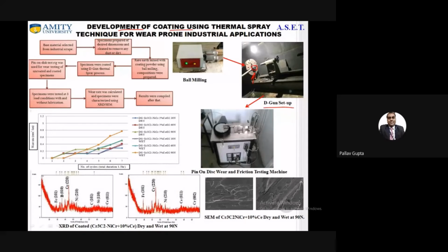So next, we have studied the wear characteristics, in which we have done the wear characterization at variable load and variable conditions. That means wet condition, dry condition, semi-wet conditions, all these conditions we have done the characteristic studies. And then we found that for the 5% and 10% addition of cerium oxide, the 10% addition of cerium oxide in both chromium carbide nickel chrome gives superior coating characteristics. And that has been verified with these particular SEM micrographs also.